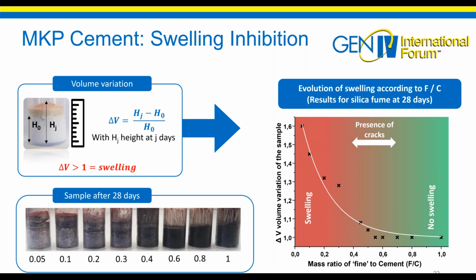The photographs on the left, at 28 days, show that the swelling decreases and disappears with the increase of fines. This is more visible on the graph. The area in red corresponds to formulations with swelling and in green without swelling. Between the two zones, the samples show cracks. These results are identical whatever the final use. The formulation with a mass ratio of fines to cement equal to 1 has been chosen for my work.